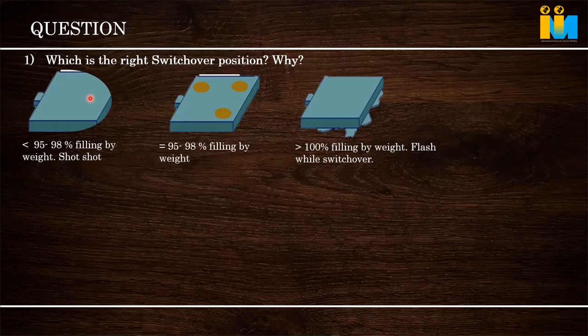I will tell you. In an injection molding machine, the mold closes. Full tonnage will not be applied at that time, because inside the cavity nothing is there. There is no pressure built up. When the raw material fills the cavity, then pressure is built up and the mold tends to open. If you are filling the part more than 100%, locking tonnage happens when the switchover happens. At the switchover pressure point, the machine applies 100% locking tonnage.